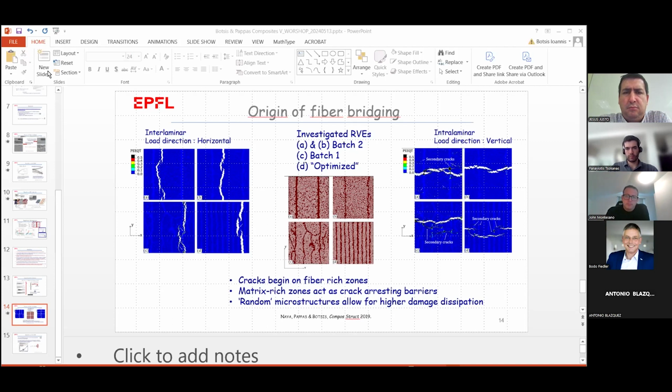And the explanation we have is that the mechanism of damage that appears in an actual structure when a transverse crack in the 90 degree layer is reaching the interface with the zero degree layer produces extremely complicated damage that interacts with each other and produces low values of this property, which questions the application of the value obtained from a DCB test. You wanted to say something?